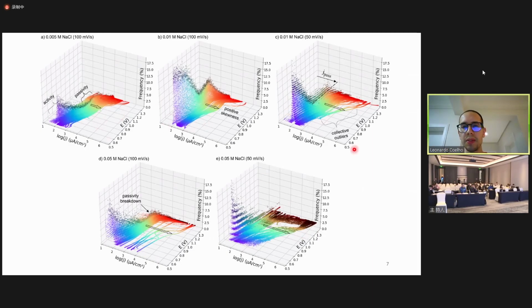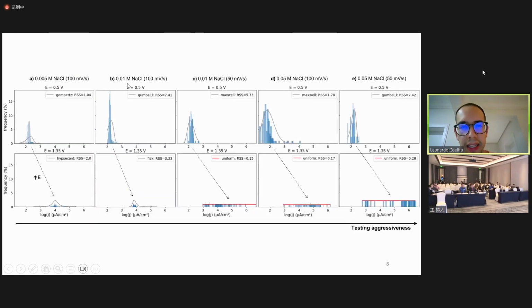As you see, as we increase the aggressiveness of the test, we tend to get higher spread and wider and wider distributions. These are simply 3D histograms where we plot the histogram of the current density that we measure, and that represents corrosion, as a function of applied potential. And we realize that at low applied potential, as you can see on the top, the distributions, although not quite normally distributed, tend to follow a unimodal type of distribution. And as we increase the aggressiveness of the test, the distribution tends to diverge, and the spread is much higher. And in fact, it increases the likelihood that we can fit the distribution by the uniform distribution.